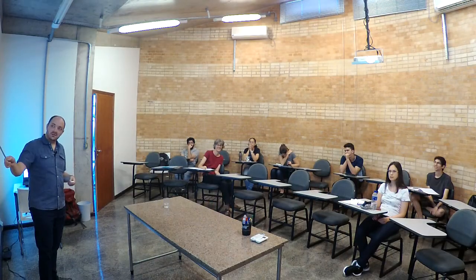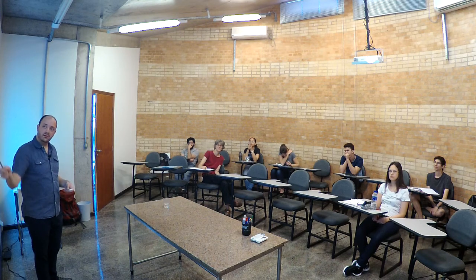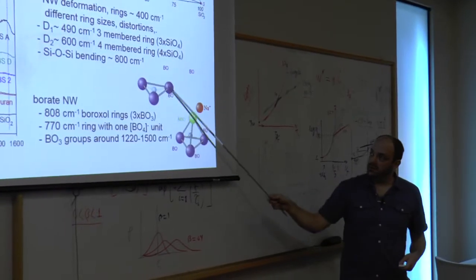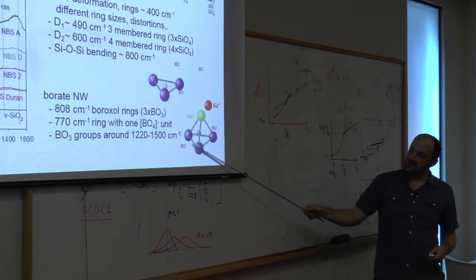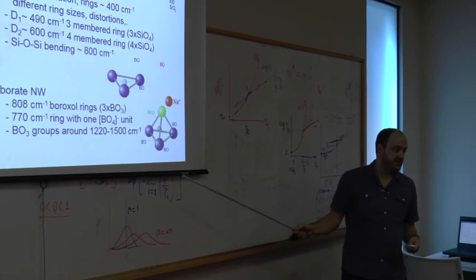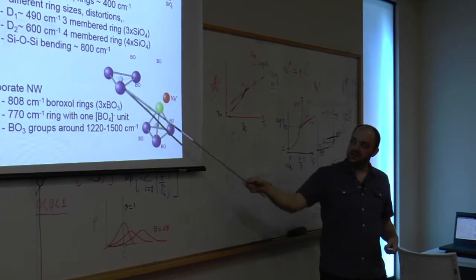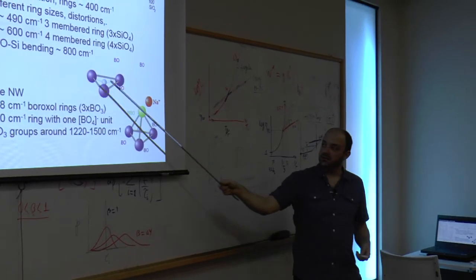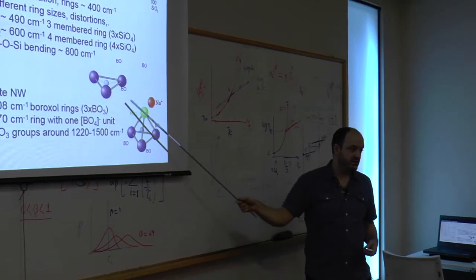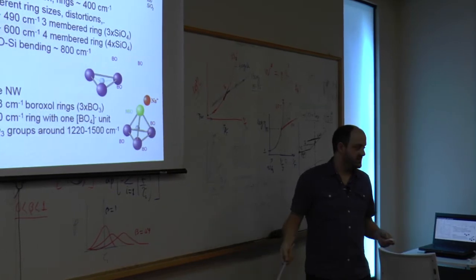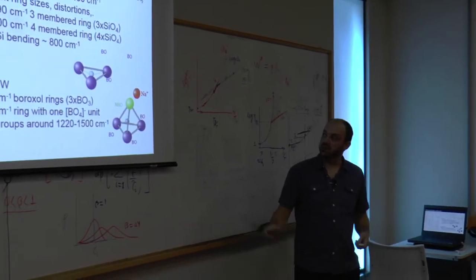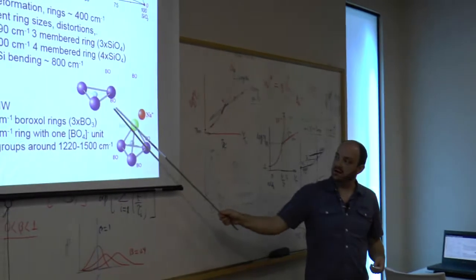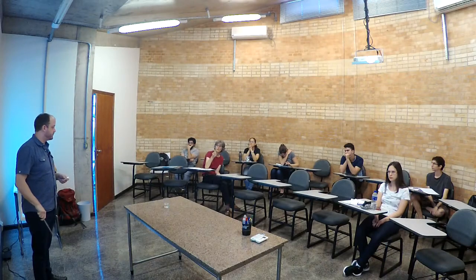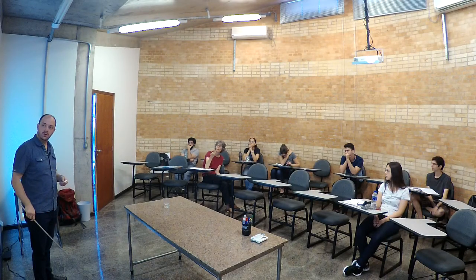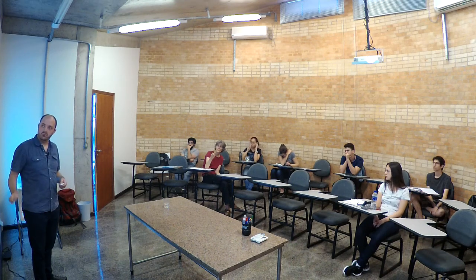And the other key feature is that with boron, you get 3-member planar units of BO3 versus BO4 tetrahedrons. I don't know of any paper that suggests this kind of configuration for silica. So when you mix them together, it gets complicated. But these are still network formers, even though it's not a tetrahedron. Yeah, but the BO4 tetrahedron doesn't have a non-bridging oxygen. Okay.